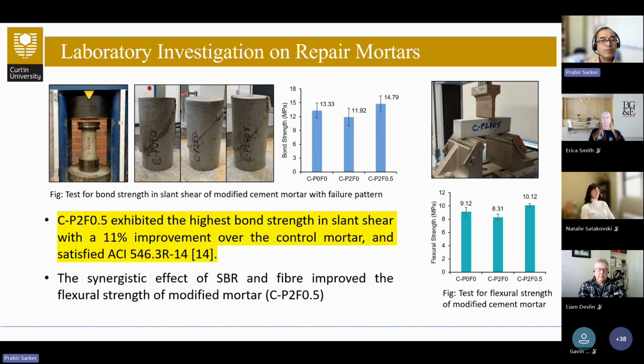This is still the mortar that we produced in the lab. What we see here is that bond strength and flexural strength both actually increased by the combined use of the SBR and the fiber.